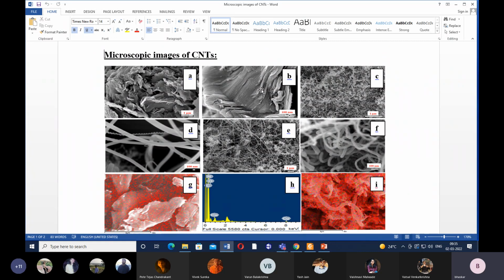And next I had to perform the reduction. But remember, since our support is carbonaceous in nature, I couldn't carry out the calcination in an air atmosphere. I had to use a nitrogen atmosphere to prevent the burn off of the graphite into carbon monoxide and carbon dioxide. Okay, so the next step was the reduction operation. What was the purpose of the reduction? We converted copper oxides into their elemental form, so from copper oxide nanoparticles, I produced copper nanoparticles, and those copper nanoparticles resided on the surface of this graphite powder.